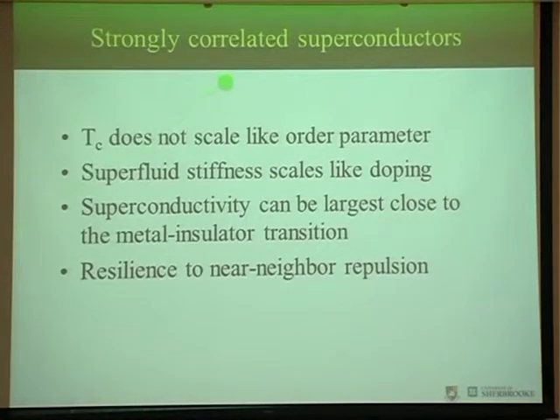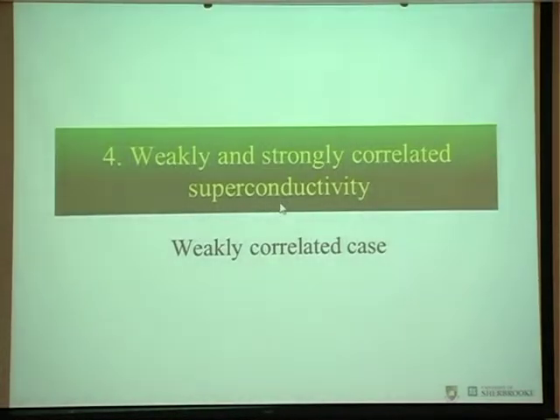But there are things that are more specific to strongly correlated superconductivity. For example, Tc does not necessarily scale like the order parameter. Superfluid stiffness scales like doping a Mott insulator instead of filling. Superconductivity can be largest close to the metal insulator transition. And what I will mostly discuss in this talk is resilience to nearest neighbor repulsion, which is very different whether you're weakly or strongly correlated.